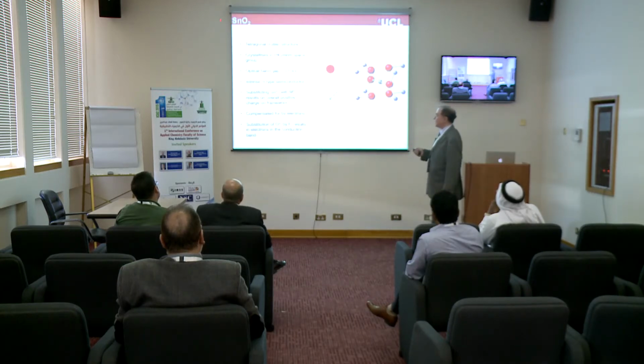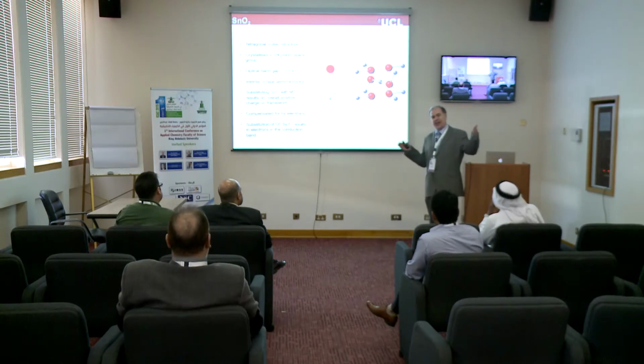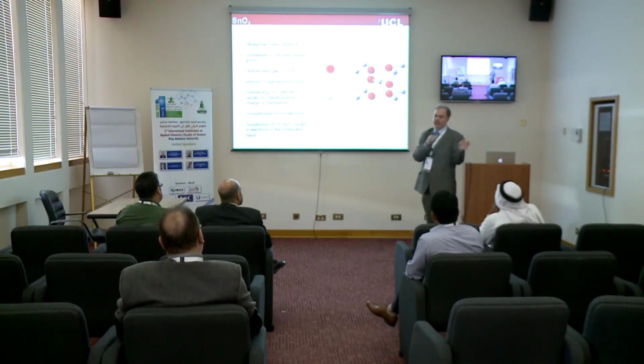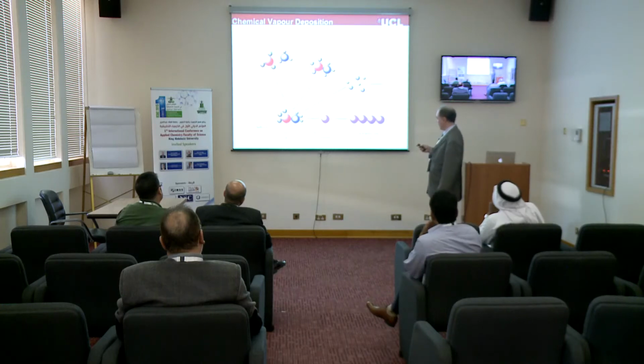The first one's related to tin dioxide. Tin dioxide on a window surface is used to make what's called a solar control coating. It's no good for this country because it's too hot, but in the UK where it's cold, these solar control coatings help to reflect heat back from a window into the building and keep the building warm when it's cold. And so this is based on tin dioxide, of which the structure is shown there.